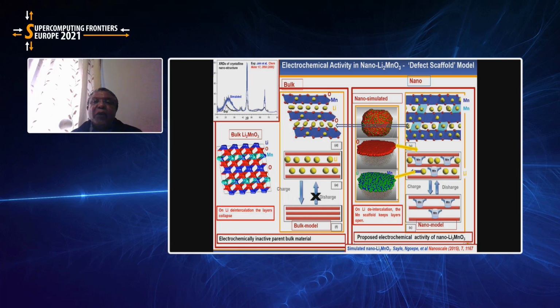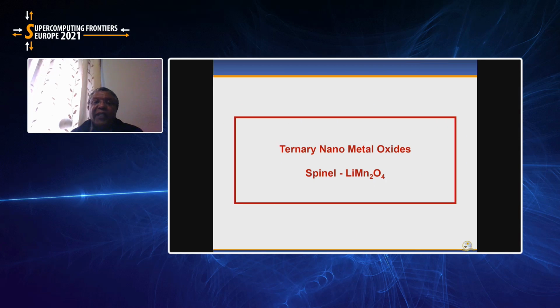However, if you make them nano, then you introduce some of the manganese into these layers, and ultimately the manganese in that layer acts as a pillar. So as you charge, you remove the lithium, and the manganese remains a scaffold that keeps the layers open. Then this is open for discharge and charge, and in that process we are able to use this as an electrode. So that is the origin of the electrochemical activity.